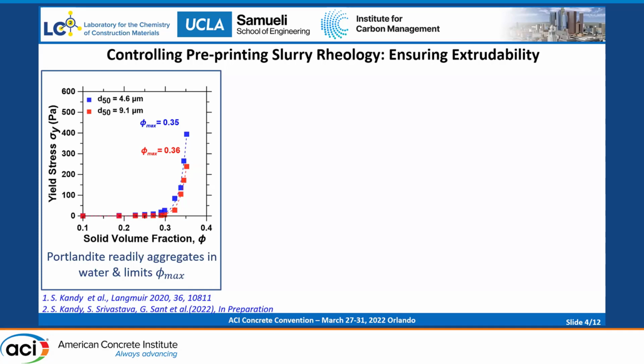So if we use this suspension for printing, we'll have high drying stresses, high porosity, and mechanically weak structures. So having a high solid content and an optimal rheology is crucial. So we need to improve this.